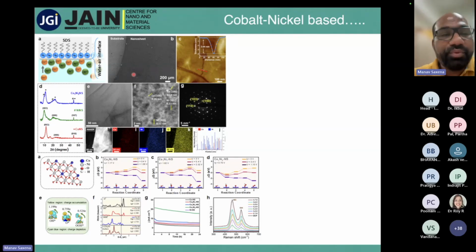So what we have done, we have taken a solution of cobalt and nickel ions, and with the same process we have made a sheet, and we have achieved the thinnest sheet of around 3.6 nanometer. We have analyzed it with XRD and TEM. You can see that it is crystalline in nature. The SAD pattern also shows that it is crystalline, and TEM also shows it is uniform.